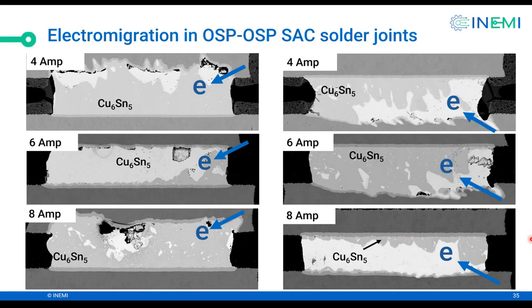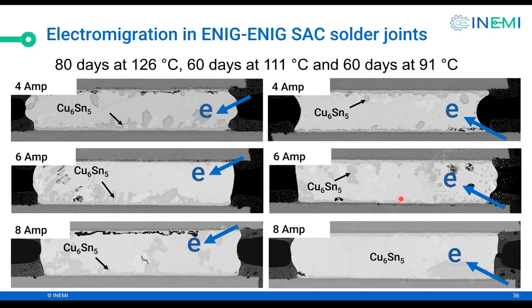So notice, if you look at these charts, they don't seem to make sense. There's not much electromigration here, not much over there. Why do you have so much here and here and here? I don't know. But I think it has to do with the copper getting into the solder. The more copper into the solder, the thicker the intermetallic. And this one is ENIG.